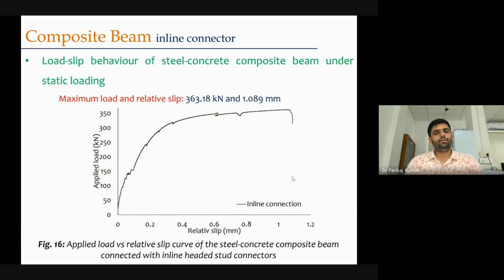Later on, when we look into the behavior and the applied load versus engendered slip in the case of the mechanically connected steel concrete composite beam, the ultimate capacity of the beam was roughly about 363 kilonewton with 1 mm relative slip. There were 3 criteria we selected to assess the performance of the composite beam. Of course, there are many, but out of them, one we took as capacity, second the slip, and third the deformation, because when we look into the limit state of serviceability, deformation is also an important criterion, and the initial stiffness.